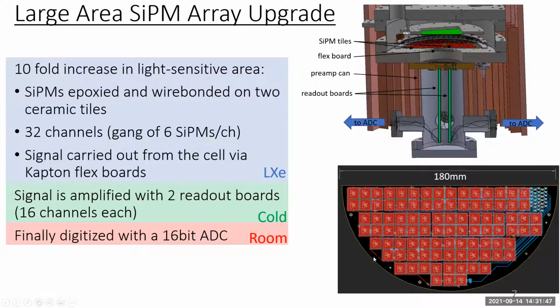In order to do this, we built a ceramic tile, and we populated it as much as we could with SiPMs. We were able to pack into 2 semicircular tiles of 180 millimeter diameter a total of around 200 devices, divided in 32 different channels with 6 SiPMs per channel. The signal is still read out by 2 electronic boards at cold temperature, not in liquid xenon, just cold. After this, they are sent out at room temperature for the digitization by the ADC.